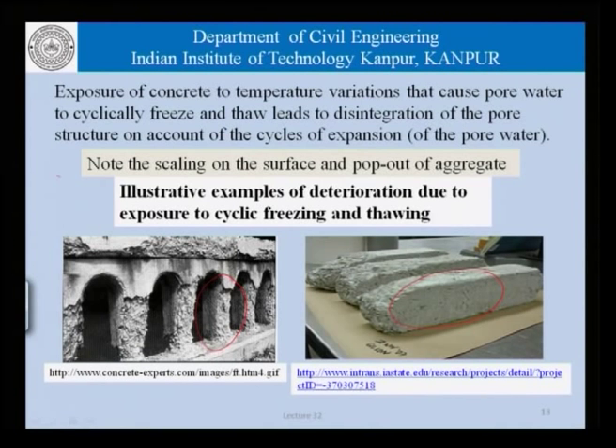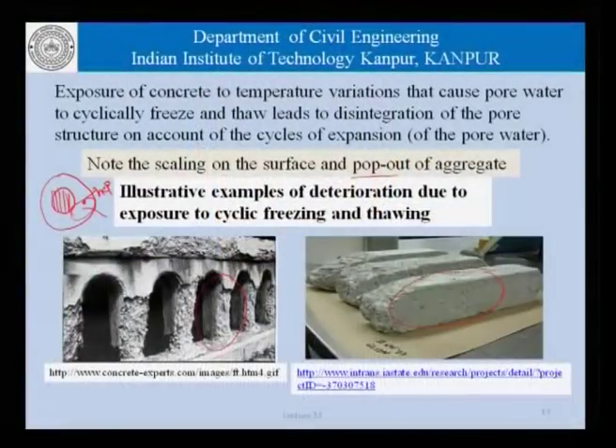What really happens is that if we have an aggregate sitting inside hardened cement paste, on account of cyclic freezing and thawing, this pore structure of HCP is the one that will disintegrate. The aggregate itself is not so vulnerable, even though it has its own porosity, but it is the HCP of the cement paste which is vulnerable, or at least more vulnerable. On account of repeated cycles of freezing and thawing, the HCP disintegrates. If the HCP around the aggregate disintegrates and gets removed, then the aggregates become unlocked from their matrix and we have a pop out of aggregates.